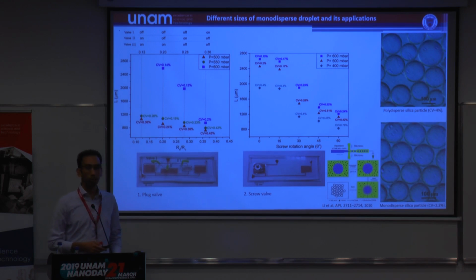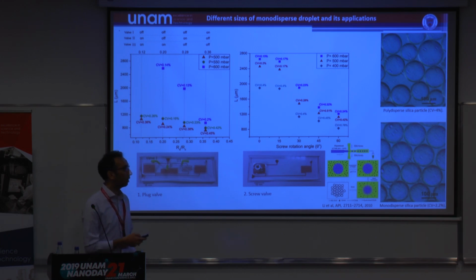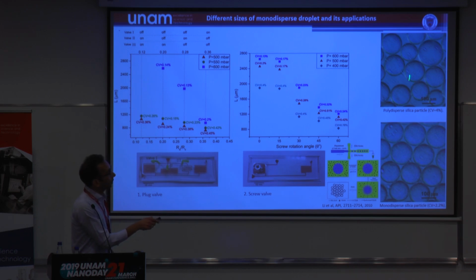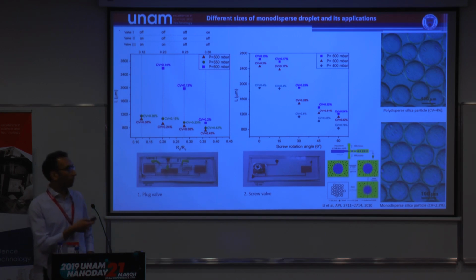As an application, we made a silica particle with traditional method and our proposed method. With traditional method, the CV of those particles was equal to 4%. It is obvious different size of the droplet on top. And for monodispersed silica particle, we got CV equal to 2.2%. And as you see, they are very packed and lattice shaped. And there are some applications for that.